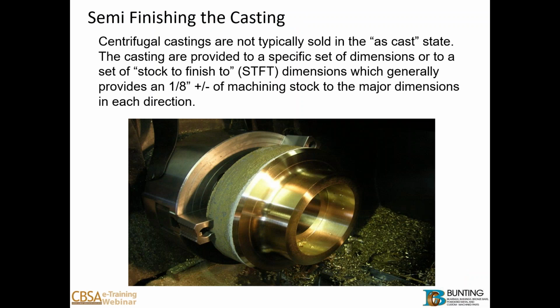So we've walked through the process of melting the material, checking chemistries, preparing the die, pouring into the die, making the casting, cooling, and extracting the casting. Afterwards we take that casting as is, we call it an as cast, to the machining area where we then semi-finish it. As I said earlier, it's not common in our industry to ship an as cast casting for fear of finding porosity or some issue along that line, and also the clients don't want to pay for extra material they don't need. So this is just a pictorial of a casting on a machine being semi-finished down.